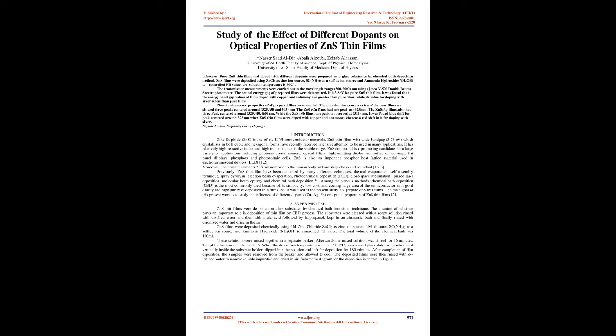It was found that the energy band gap values of films doped with copper and antimony are greater than pure films, while its value for doping with silver is less than pure films. Photoluminescence properties of prepared films were studied.